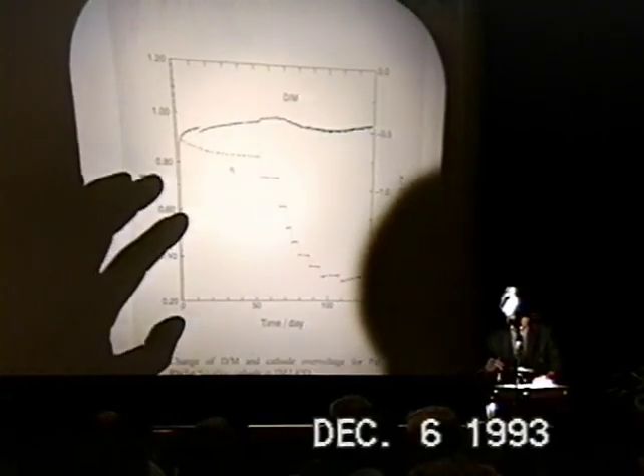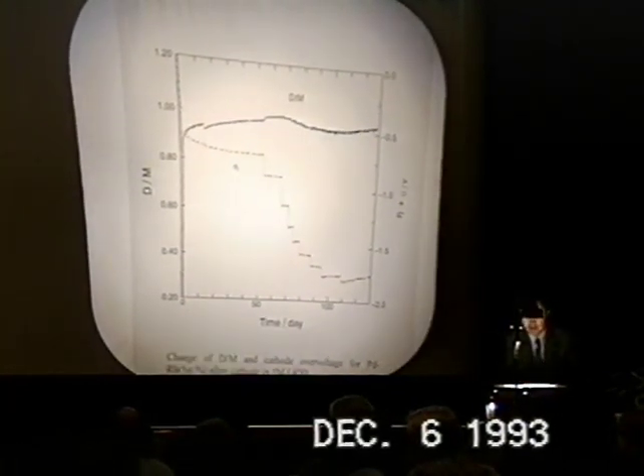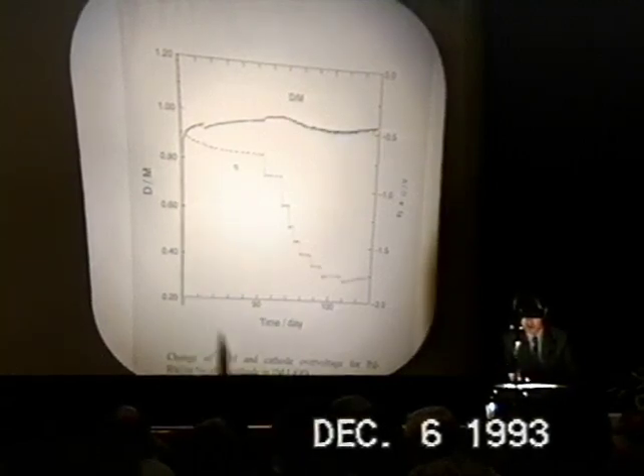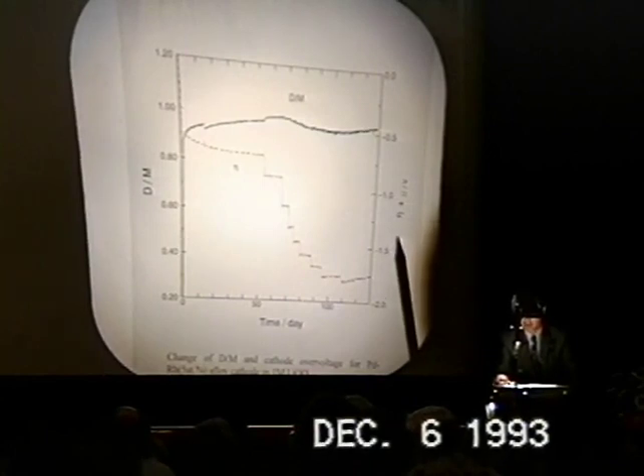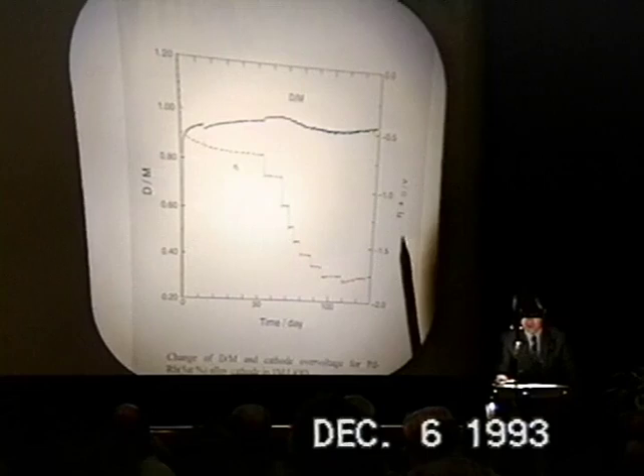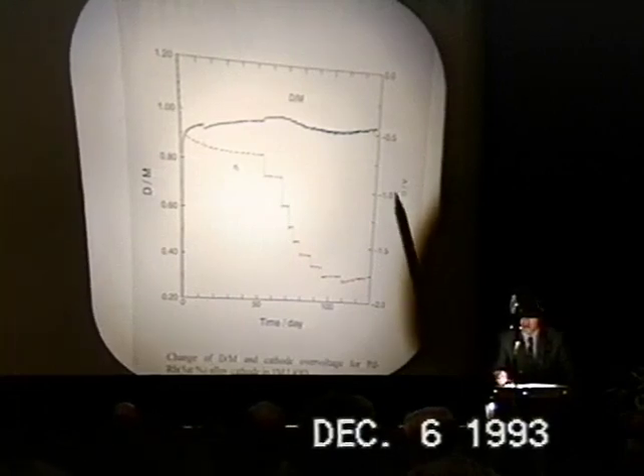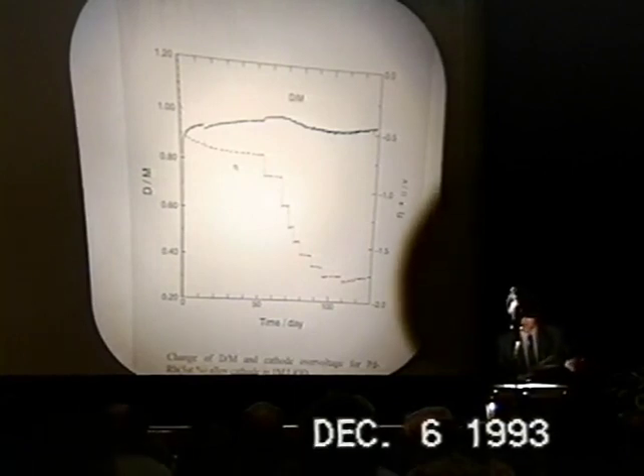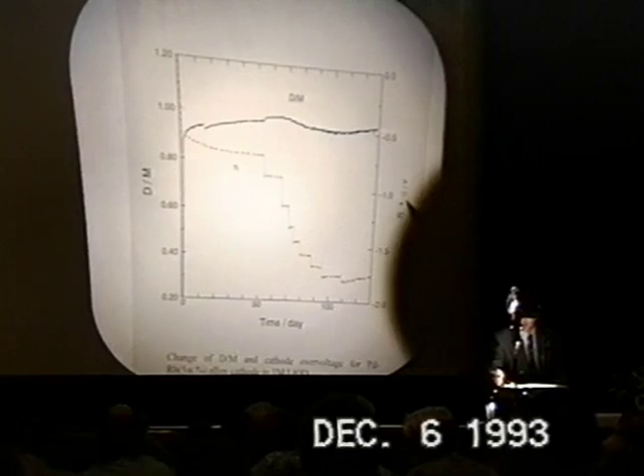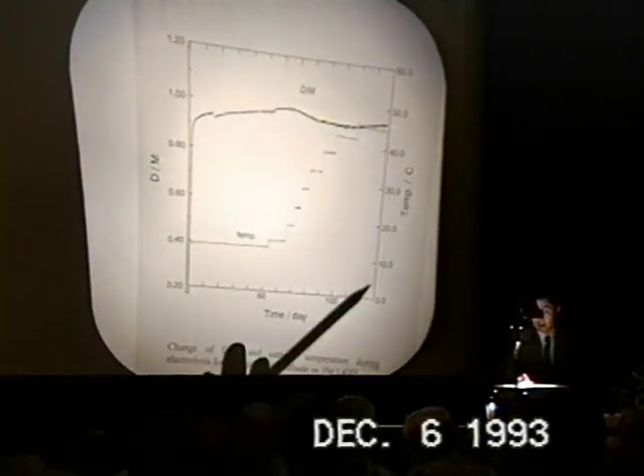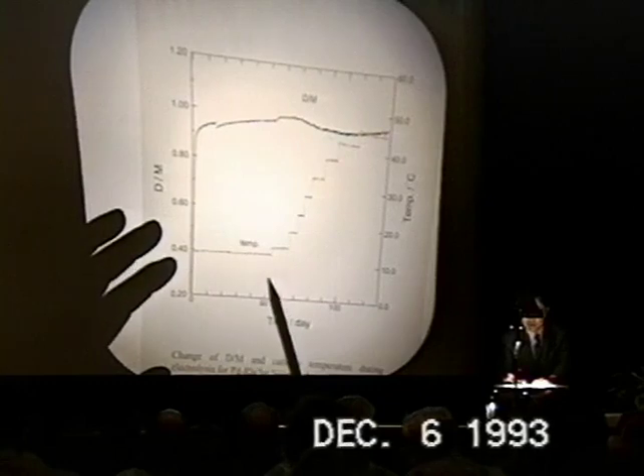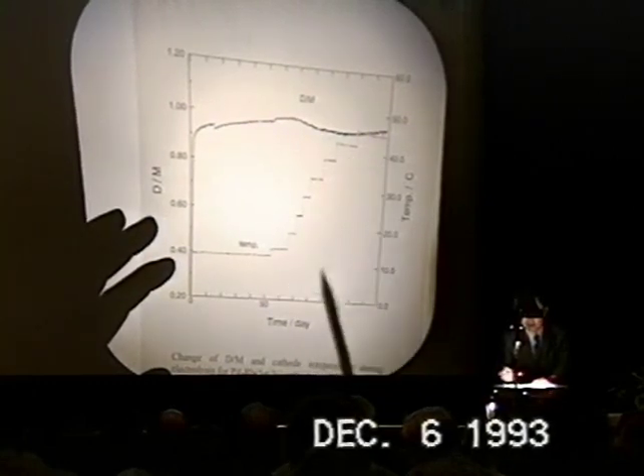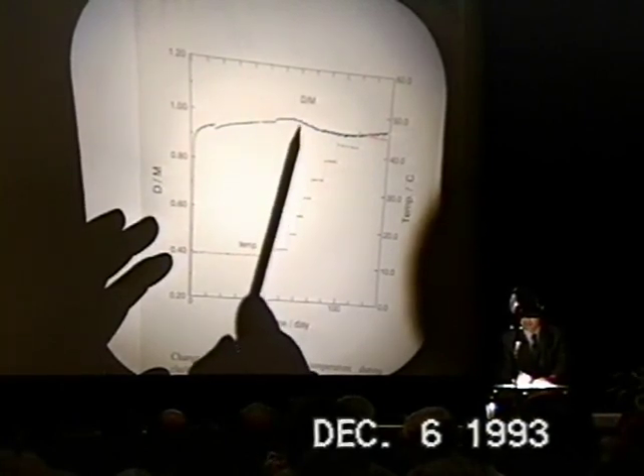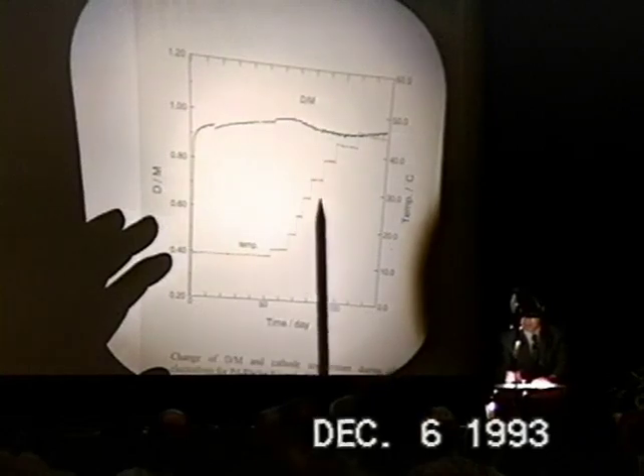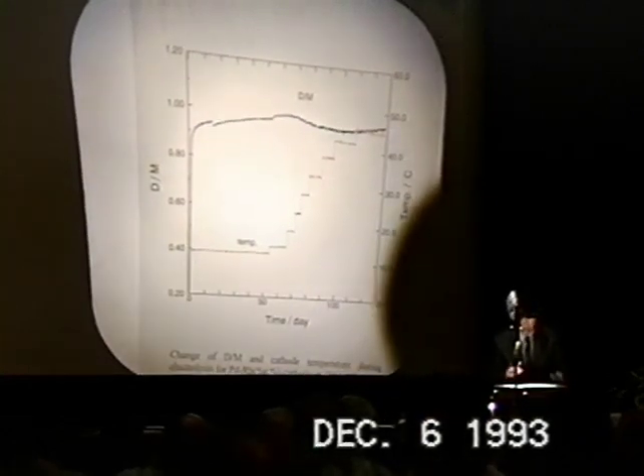If we show the same data with the data for hydrogen overvoltage, we have this. But although we have not excluded the ohmic overvoltage due to solution resistance, so this is the total hydrogen overvoltage, including ohmic overvoltage. The reason why we cannot eliminate it is we are still continuing this experiment. The temperature during this period increases in a stepwise manner. So the reason for the deloading slightly after loading ratio 1.0 is probably because of the higher temperature in the electrolyte.